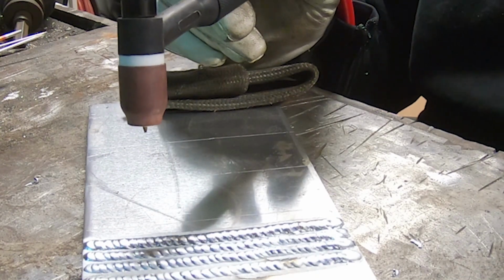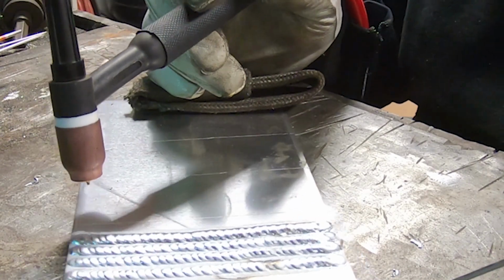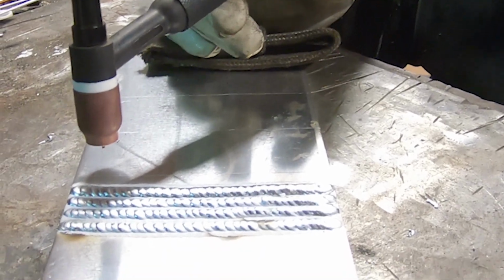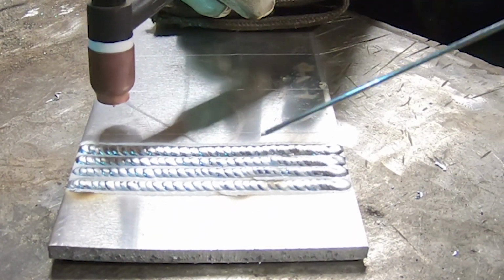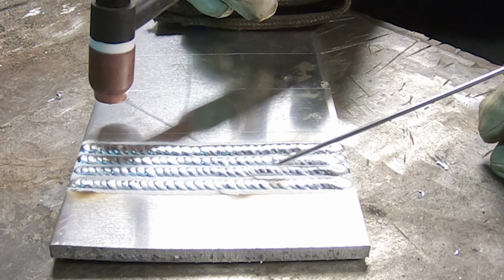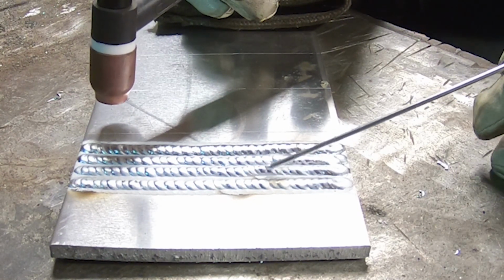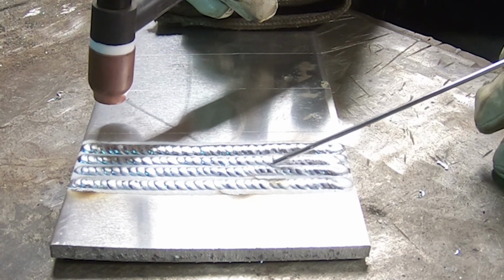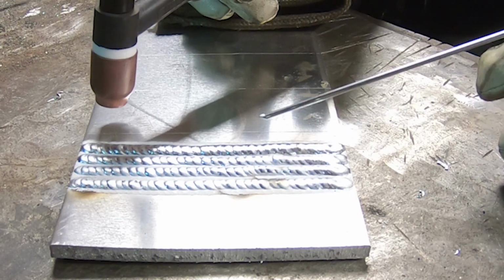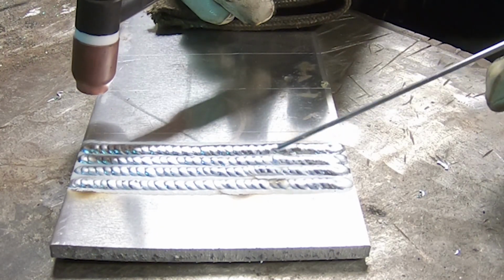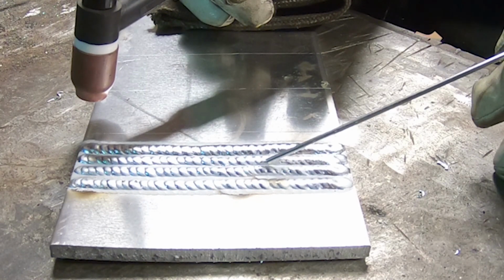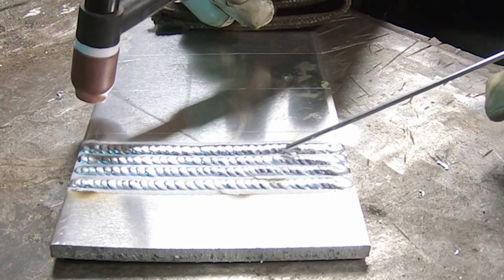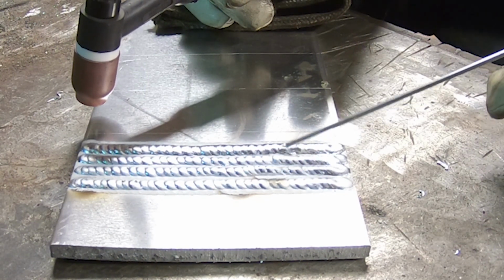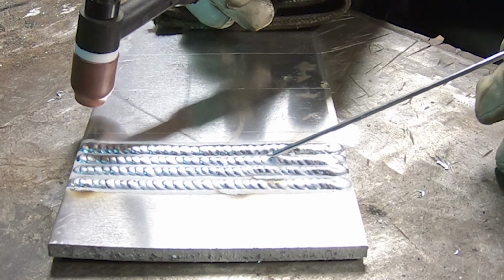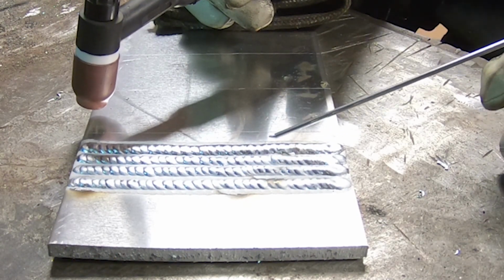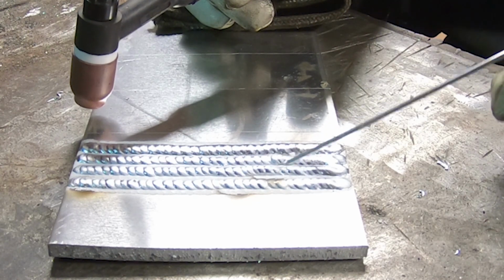Let me use this as a pointer. On the second bead right here, hopefully you guys are seeing this, you can see that it's raised up quite significantly. Now that barely penetrated that metal whatsoever, and if I cut this in half, which I might do later, you'll see that this right here is actually no penetration whatsoever. Same thing with where I dipped the tungsten in the puddle. On this side here you got tungsten inclusion, which will cause porosity and all kinds of other stuff.